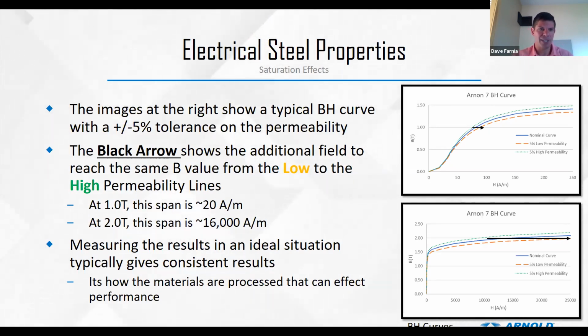If we take it into 2 Tesla, and again, this is excessive saturation at this point for a silicon steel, that distance can go to 16,000 amps per meter. So if you're really trying to operate in heavy saturation, predictions should be taken with a grain of salt, because that performance can be dramatically affected by the way that the material is processed, and then that resulting performance can be much different than what you would predict.